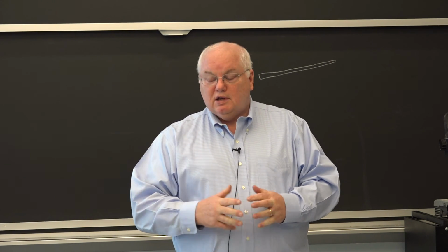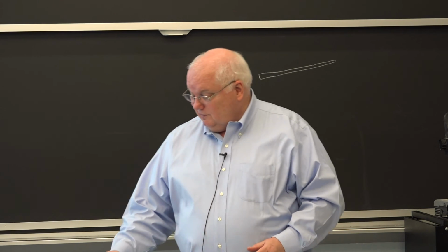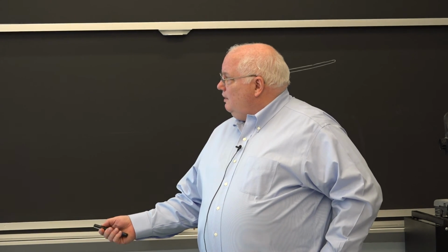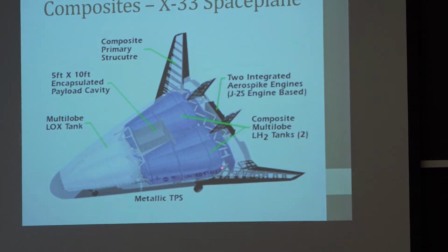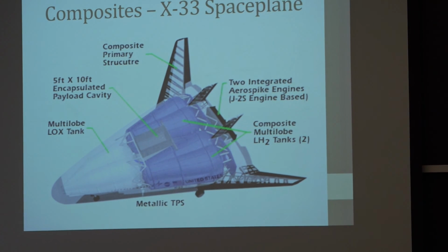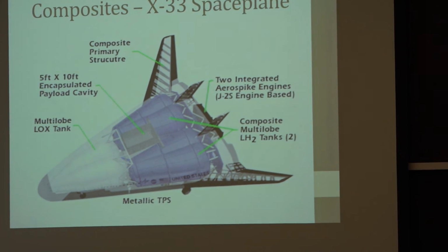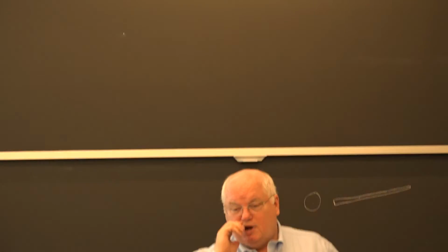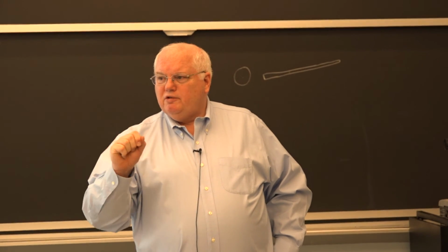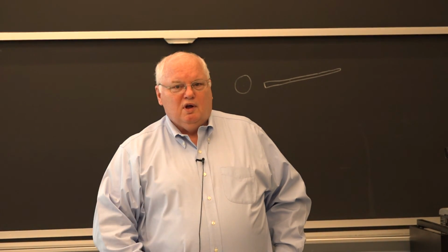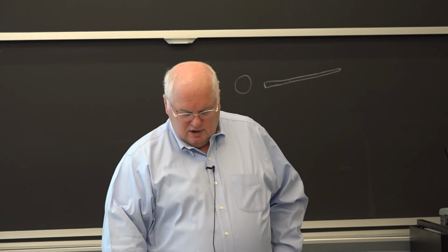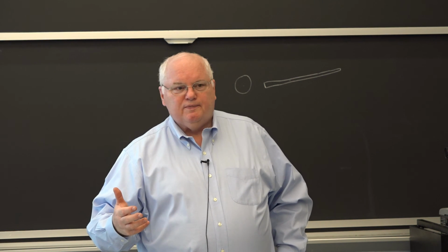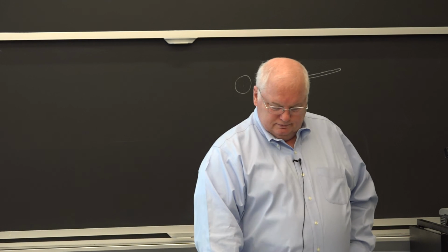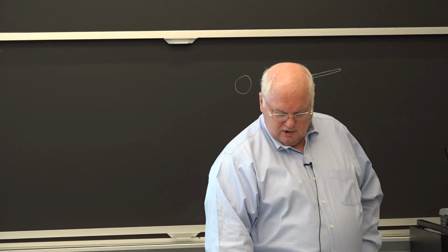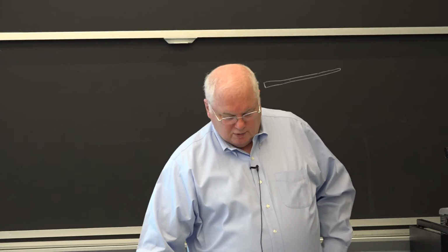So they had designed this thing. They can't go too big because it's heavy, okay, to make things safer. And they designed it for 2.0, but because of the delamination during autoclaving, they found they only had 1.05, but this is a $1 billion project. 1.05 is greater than 1, and so it should work. So they took one of these tanks, and they put it in test in Huntsville, Alabama, and we'll talk about the test in a second.